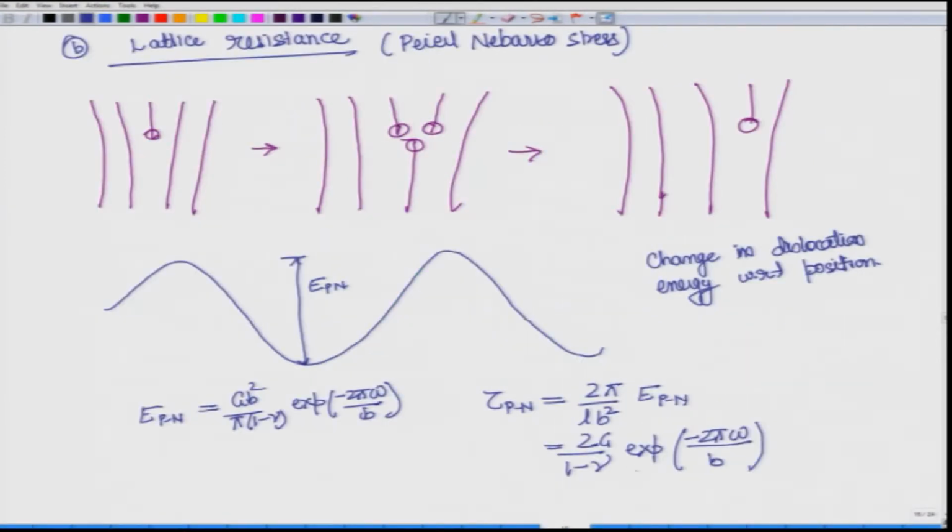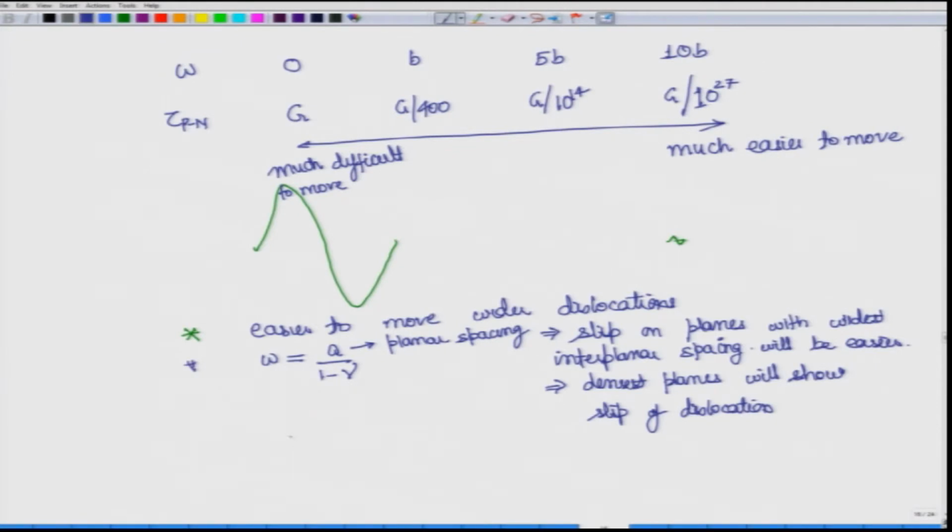Another aspect that you see over here is B. So, this also gives us some information. B is the slip direction. So, we have talked about slip plane, we saw that slip plane has to be the densest plane. Now, B is in the denominator, so this has to be very small. If it is small, then this negative quantity is large, and therefore, tau Pn is again small. So, for B to be small, where is the B smallest?